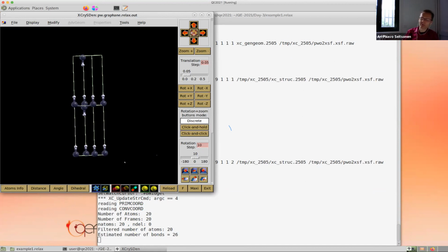And then the question is, how much space do you give? Some people take 6, 7, 8 angstroms maybe. Is it enough? It was mentioned that, for example, if you have a dipole in your system, it converges much slower, so you might have to go to algorithms which take a weighted dipole.